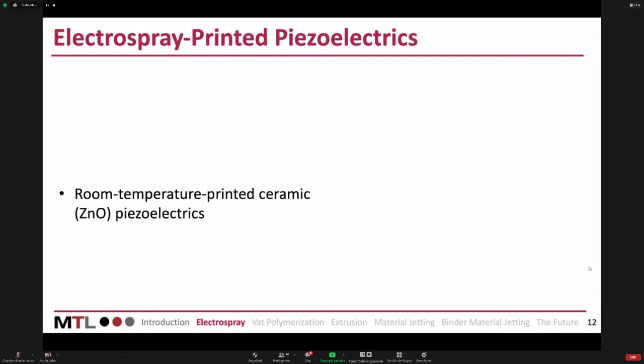But in order for that to be efficient, you need specialized manufacturing and also very pure material. That quartz crystal is a single crystal. So there are a lot of people that have tried to do piezoelectrics that are printed, but they tend to be lousy because the quality of the material is not good. But what we have seen is that if you harness this technology, electrospray, that is not true.